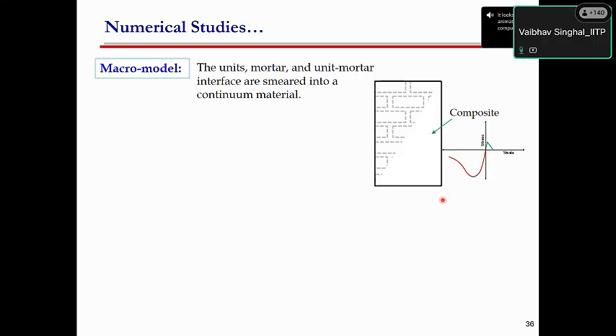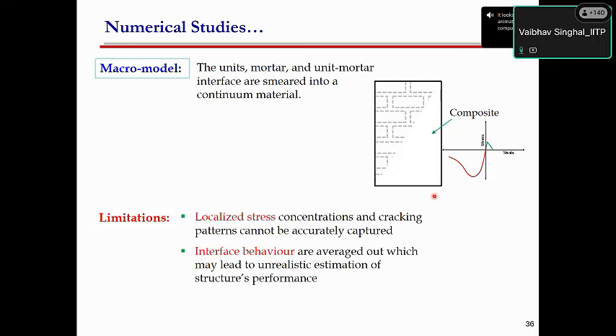The next method, a simplified one which many researchers and engineers use, is the simple macro modeling technique, where we simply model the wall as a continuum, composite element, and then define compressive properties and tensile properties. But the limitation of this methodology is that you cannot know about the localized concentration of forces and stresses. You cannot know about the cracking pattern, although indirectly one can know it using plastic strain contours. You also will not know about the various interface behavior, whether the failure will be a sliding failure or a diagonal shear failure. So it is difficult to assess those minor details from macro modeling.